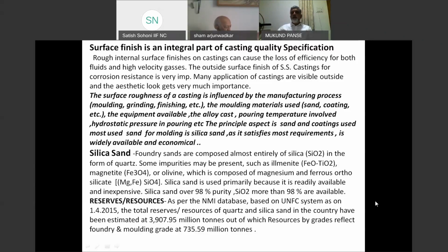The surface roughness of a casting is influenced basically by the sand you use and the molding process you use, the pouring temperatures, and the hydrostatic pressure in the pouring. The principal aspect which decides the surface finish of the casting is the sand you use and the molding method you use. The major sand used is silica sand because of its availability, and it meets most of the requirements.